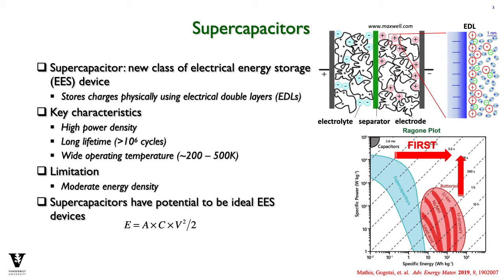Supercapacitors have long lifetimes. They can be cycled millions of times, while batteries are typically limited to about 1,000 times due to degradation of the electrode. Since supercapacitors do not react chemically with the electrode, it does not degrade them. Supercapacitors have a much wider operating temperature than batteries. All of these characteristics are the result of the energy storage mechanism being based on physical adsorption of ions into electrodes. This is also the reason for the primary limitation of supercapacitors, moderate energy density. So how can we improve the energy density of supercapacitors?